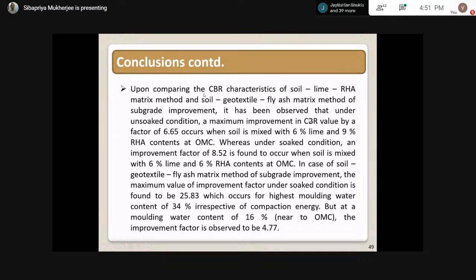Now, upon comparing the CBR characteristics of the soil lime RHA matrix method and the soil geotextile fly ash matrix method of subgrade improvement, it has been observed that under unsoaked condition, a maximum improvement of CBR value by a factor of 6.65 occurs when soil is mixed with 6% lime and 9% RHA content at OMC. And this becomes 8.52 under soaked condition when 6% lime and 6% RHA are mixed.